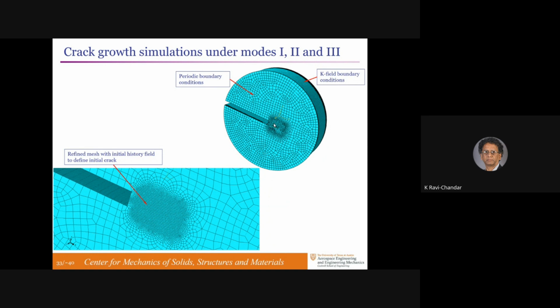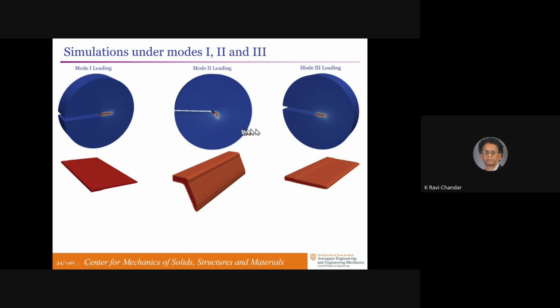If you now run this with modes 1, 2, and 3, you get the following description. If you do a mode 1 loading on it, the phase field method predicts that the crack should grow straight, which makes sense. If you apply a mode 2 loading on it, it kinks and the crack starts to grow at an angle of 70 degrees or so, again consistent with continuum predictions. So the phase field method seems to be adequate for these things. If you do mixed mode, the unresolved issue between which of the techniques is good still remains unresolved because this is within the same error bands. But if you do a pure mode 3 loading, the crack grows straight because that's the only path along which it can minimize the energy. So it goes straight. Well, we know that that's not true.